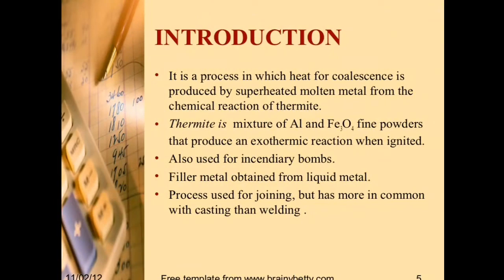Thermite Welding is a process in which heat for coalescence is produced by superheated molten metal from the chemical reaction of thermite. Thermite is a mixture of aluminium and iron oxide fine powders that produce an exothermic reaction when ignited. It is also used for incendiary bombs; filler metal is obtained from the liquid metal. The process is used for joining but has more in common with casting than welding.